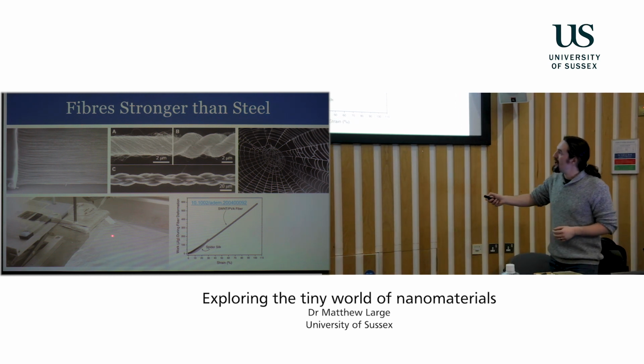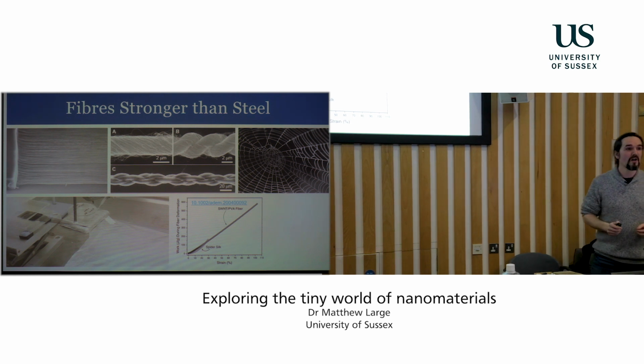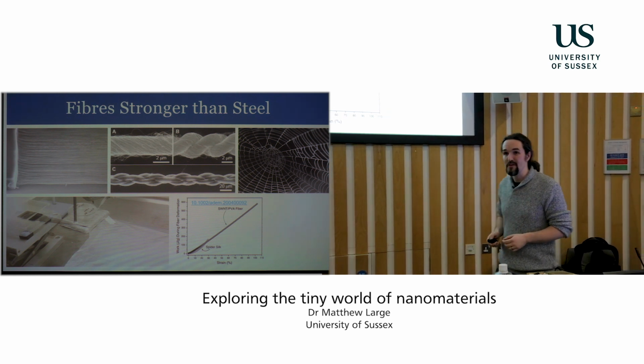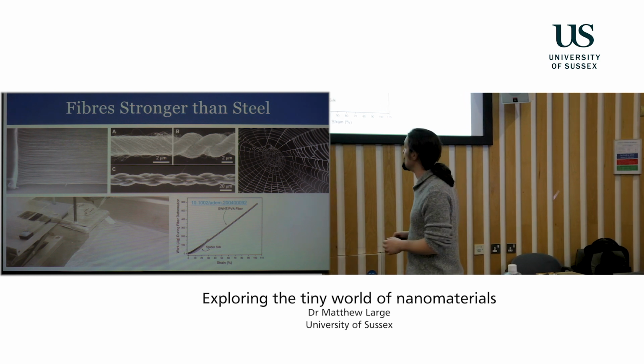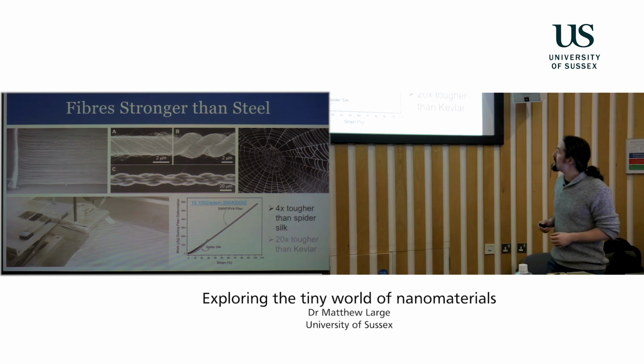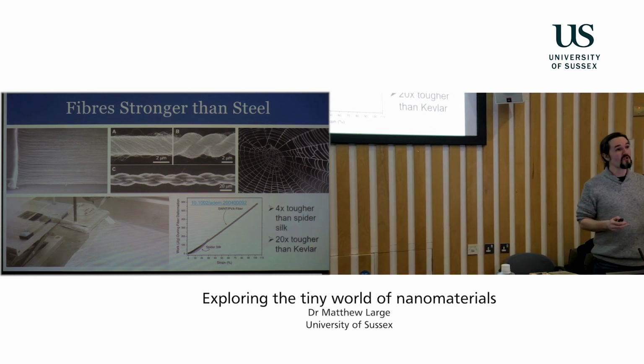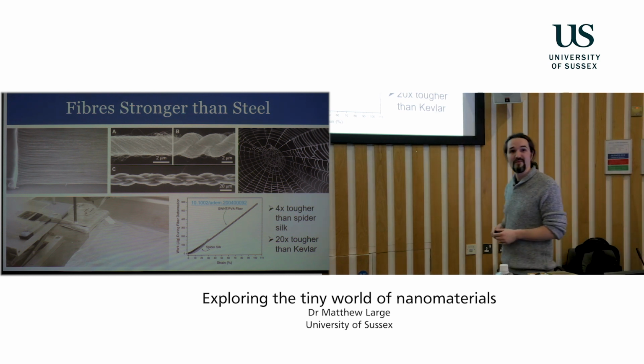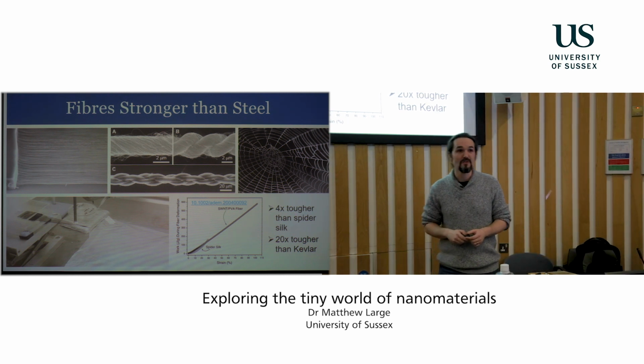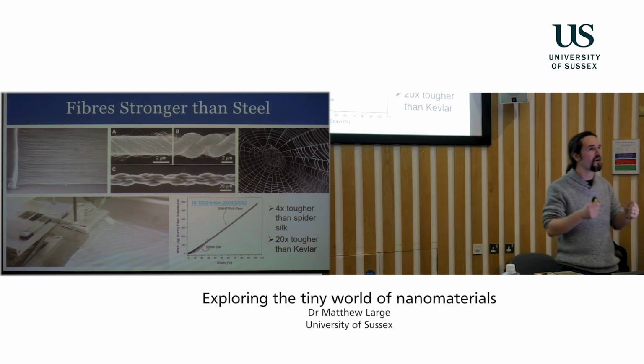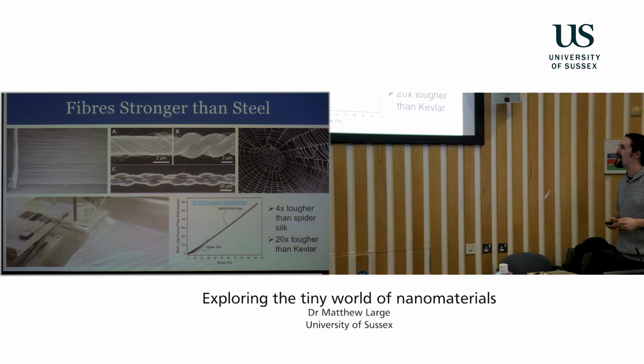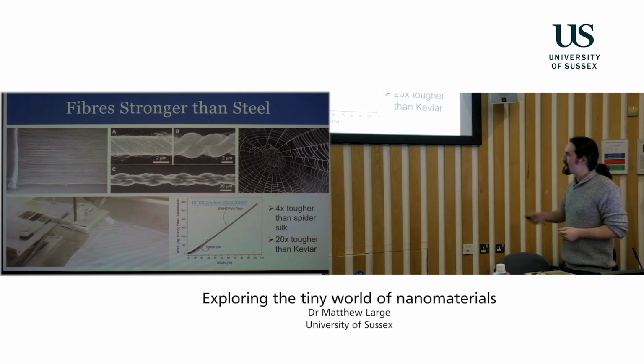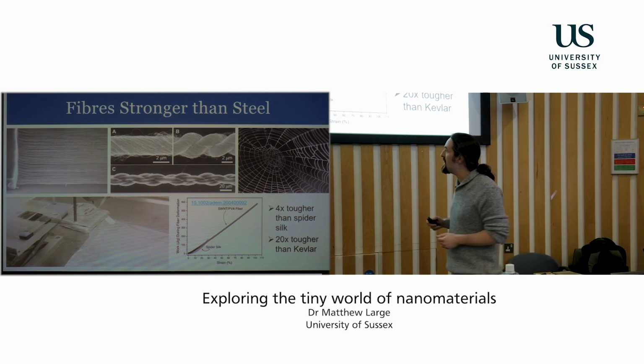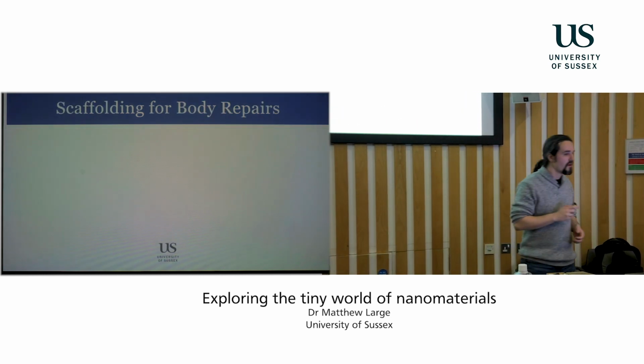But these nanotube fibres absorb 4 times as much energy. They're 4 times tougher than spider silk, which itself is stronger than steel. And that's 4 times tougher than spider silk. That's 20 times tougher than Kevlar. This is one of the strongest materials that we can make, that we can physically hold a macroscopic amount of stuff. That's really cool, but we can go even further than that.